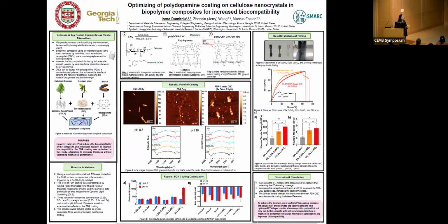With this coating, we have three variables that we're trying to target and optimize. The first variable that we want to change is the amount of catalyst that we have. The second variable is the initial amount of dopamine that we add into our system. We don't start with polydopamine, we just start with the monomer, which is called dopamine, or DA. Our dopamine, via that catalyst, gets oxidized, and once it's oxidized, it can then form our PDA, our polydopamine polymer, and it can hydrogen bond with our cellulose to form our PDA CNC system.